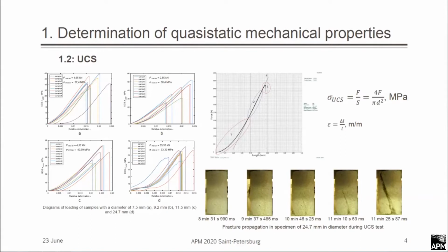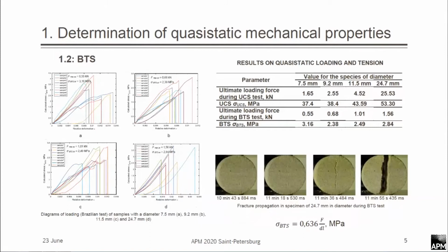and fracture mechanism. Then we determined tensile strength by the Brazilian test and noticed that the average value of tensile strength, which is presented here for each diameter, was 10 to 20 times less than the compressive strength, which is here. And we also noticed standard fracture behavior. All the experiments were performed according to standards such as ASTM and ISRM.